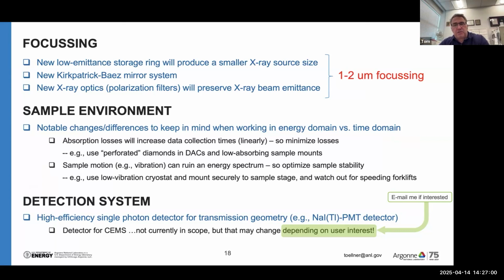For the sample environment, there's a bit of a change going from time domain to energy domain. In time domain, one has an excess or surplus of resonant photons that we have to throw away because the prompt flash on our detector is too much. So we end up putting an absorber in front of our detector to protect it. And if a user environment or sample absorbs a lot of excess radiation, we just remove the absorber in front of the detector to compensate. That approach doesn't work in the energy domain. Here we have to minimize the amount of absorption in the sample as well as in the sample environment. For diamond anvil cells, for example, the diamonds should be milled out from the backside to limit the absorption losses in the diamonds.